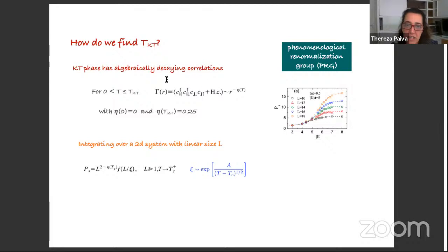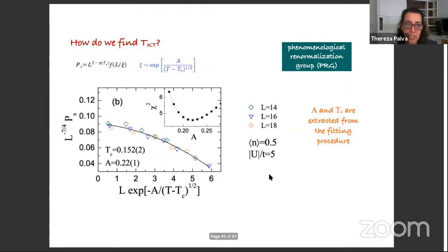And so when we integrate the correlation functions over the 2D system with linear size L, what we see is this expression here, that the pairing should go with L to the power 2 minus eta, with the coefficient here, and some function that depends only on L over ξ, where ξ is the correlation length that diverges exponentially. So we can do some plotting with L to the minus 7/4, which is 2 minus 1/4 here, and here L over the correlation length, and we should see a collapse of all the data, and this is what we see here.